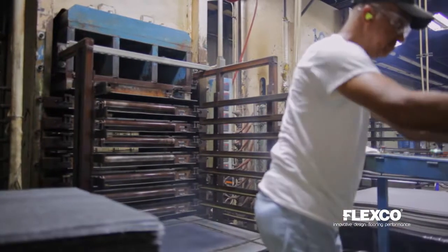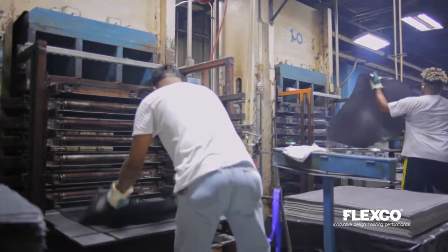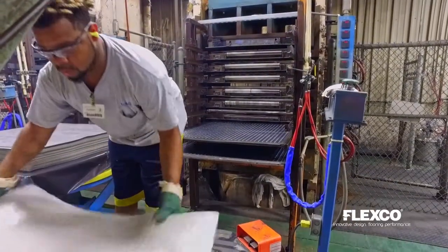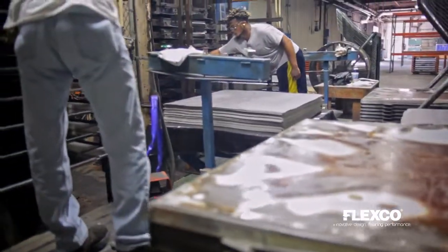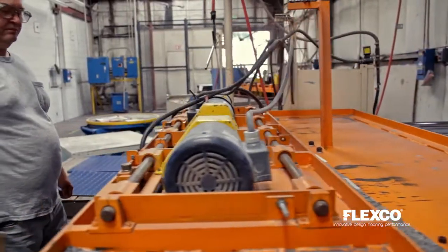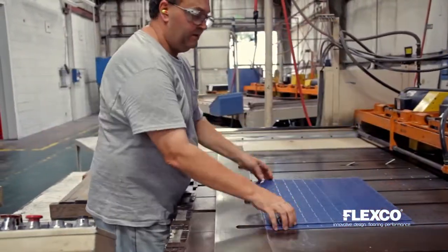Our radial tile is manufactured in a compression molding process which utilizes a prescribed combination of time, temperature, and pressure to form and cure the rubber. These tiles are made with various design textures, 2 different thicknesses, and 4 different sizes to suit your application. After molding, each piece is trimmed and sanded to achieve accurate gauging throughout the tile. The tiles are then cut to final dimensions utilizing laser-guided radial arm saws to ensure precision, dimensions, and edges.